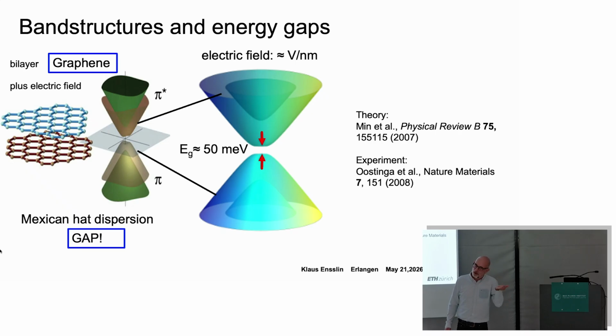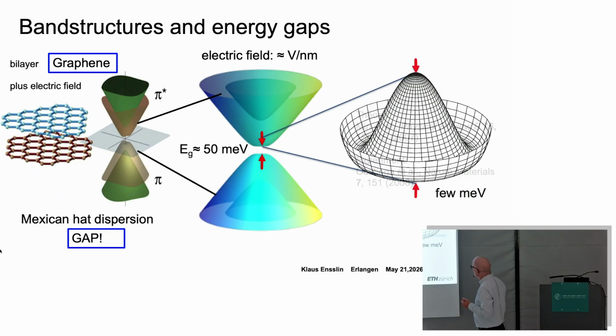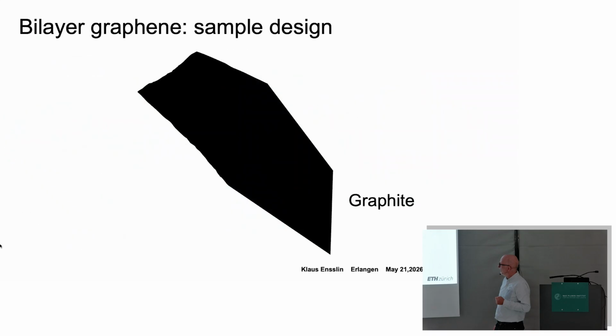And it's interesting that you can tune it with electric fields. It's a tunable band gap. And if you look in more detail, you see that you actually get this Mexican hat dispersion. This Mexican hat dispersion has a lot of interesting features. It's topology in k-space, and this topology is, again, something which is tunable by an electric field. So everything that you do in graphene can be tuned by electric field: the band structure, the details of the band structure, the band gap, and many more things, as I will explain as we go along. Okay, let me walk you through our technology.